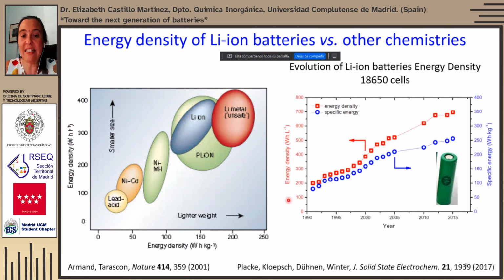If we see how the energy density of commercial 18 millimeter in diameter, 65 millimeter in height cells, these cylindrical cells, has evolved during their 30 years of commercialization, we can see that both gravimetric and volumetric energy density have increased maybe by threefold. And this increase in battery performance is due to both changes in the chemistry of the batteries as well as changes in the engineering aspect.